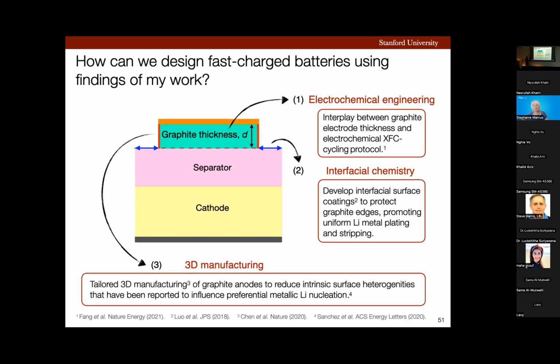Third, the edges of the graphite anode were the most prone to forming lithium. Can we use 3D manufacturing to tailor the design of these edges so that we can reduce their intrinsic surface heterogeneities, such as porosity, tortuosity, what have you, which has been reported in literature to induce preferential metallic lithium nucleation? Now, these are the three potential avenues where my work can contribute to helping us design a fast charge battery today.